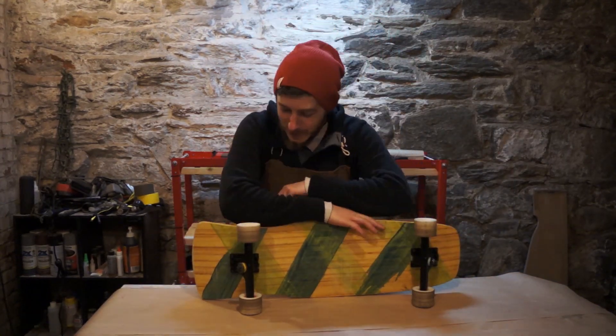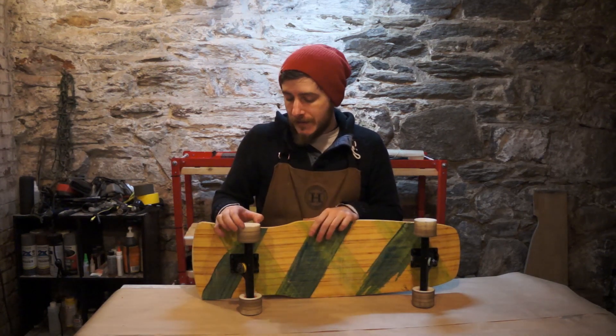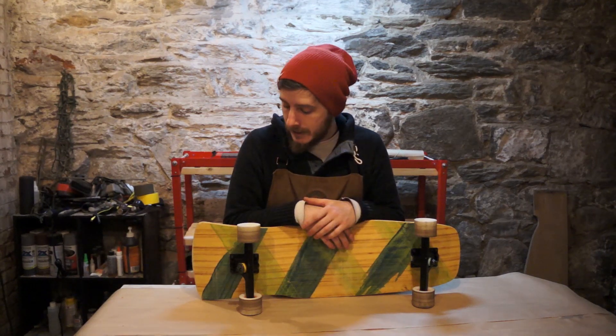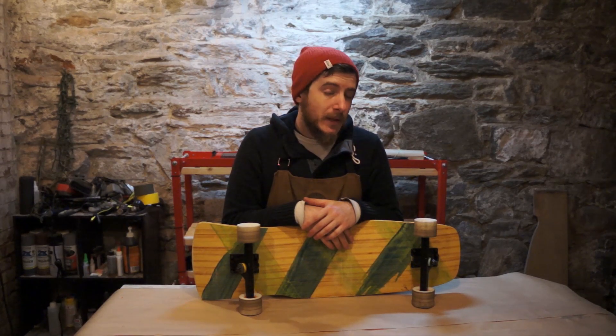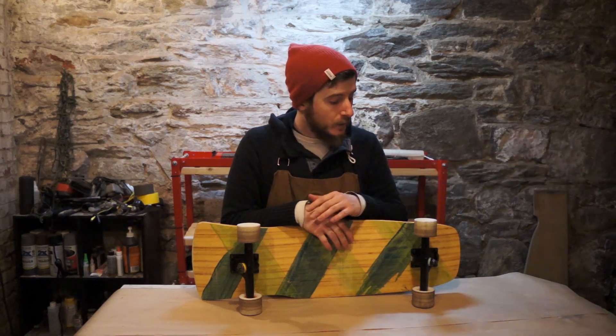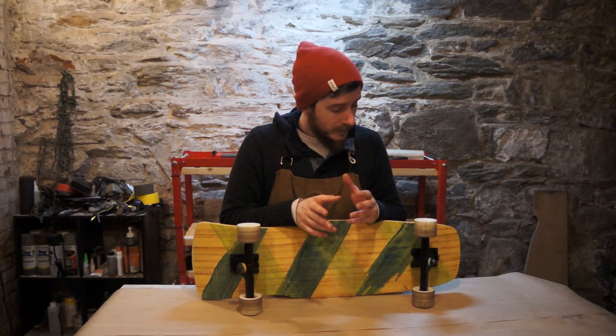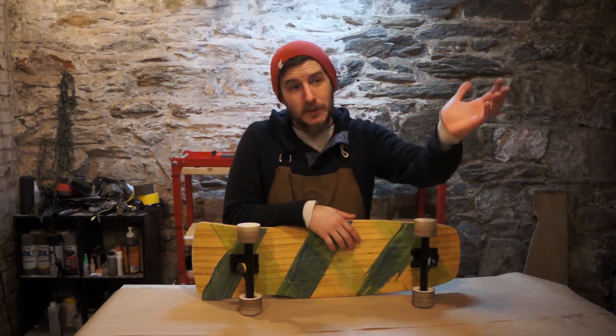They work! Super exciting! Let me say a little bit about how they ride. They roll very smoothly. They do feel like a little bit softer than a 95A wheel, and that might just be a result of the fact that the material was 3D printed and not cast in place — there's probably some air in there, probably some places where the layers don't quite meet up on a microscopic level. The one downside for now is that they don't hold speed very well. Every push doesn't get you as far as a traditionally manufactured set of wheels would. If you're going downhill, when you get to the flat your speed doesn't carry as far — they don't hold momentum very well. But when you're going downhill or in the push, they feel just like other wheels, and I quite like how they ride. They corner well, I like the way they grip, and once you've got some speed built up I like the way they flow.